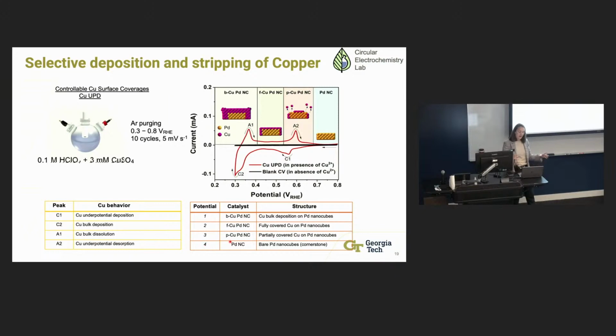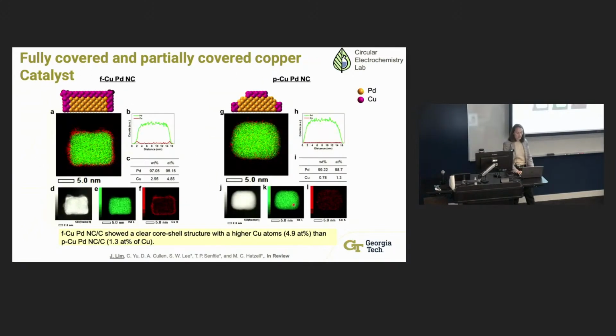And so what we started out with looking at is just taking those nanocrystals that had that 100 facet and seeing if we could basically deposit copper. This is some high resolution TEM that we went to Oak Ridge to do. What we were able to show is that you do have palladium in the core, which we expected. The surfaces do seem like they are shifting a little bit. We want these really flat surfaces for the 100, but it does seem like especially the corners are starting to shift. But we do seem to have the copper at the edges.